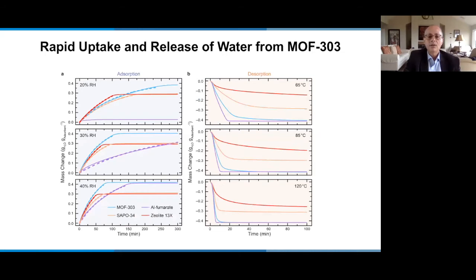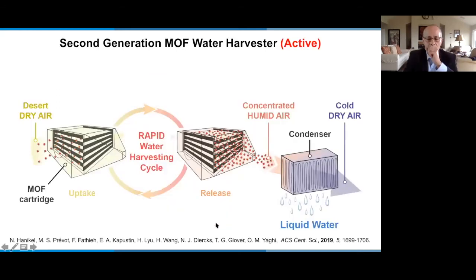The nice thing about the MOF is that not only does it take up water at low humidity, but it also releases the water much more easily than any other material. This is the blue line, as you can see here. Within minutes, the water can be released in that experiment.